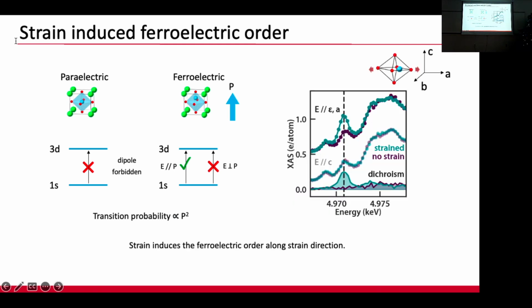And also, it's directional. If we change the X-ray polarization so it's not along where the ferroelectric order is pointing, we don't see this peak as well, as you can see from here. And we take these differences, which correspond to this ferroelectric order parameter squared.